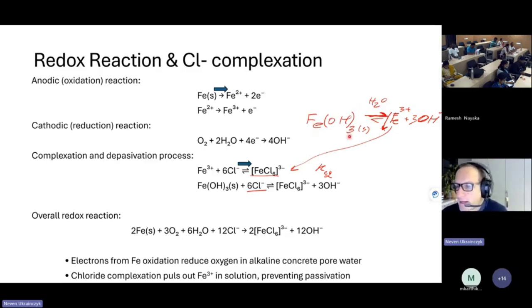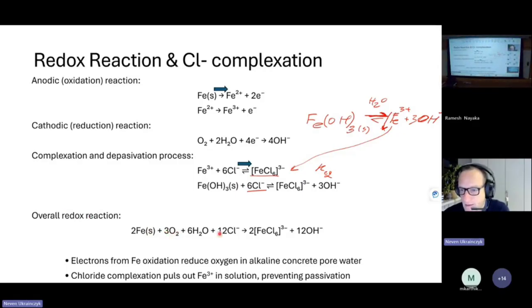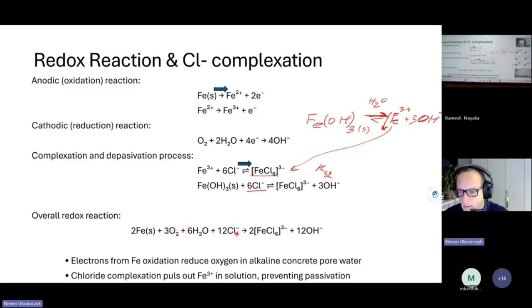So this is the same principle I'm trying to teach you, and you can see it's very important. This is what explains why the chlorides accelerate, depassivate the corrosion of steel, basically because they are making the iron hydroxide more soluble. But of course, in corrosion we also have the cathodic reduction reaction. So the diffusion of oxygen is also important, because this is then governing the total corrosion rate. So the overall redox reaction, we need chloride and also oxygen. So chlorides are important because they explain the depassivation, the initiation phase, but when you enter the propagation phase, both the chloride diffusion and oxygen are important in determining the rate of the corrosion reaction.